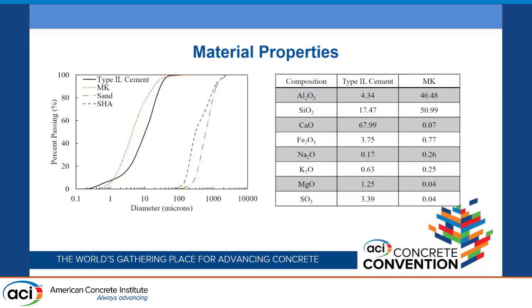As you can see, we have our particle size distributions on our left side, where we have our sand and self-healing agent of comparable particle size distributions, with our self-healing agent being slightly smaller. Then we have our type 1L cement and our metakaolin as our cementitious materials, even finer than that, forming our paste. We've also included our composition from XRF of our type 1L cement and our metakaolin.